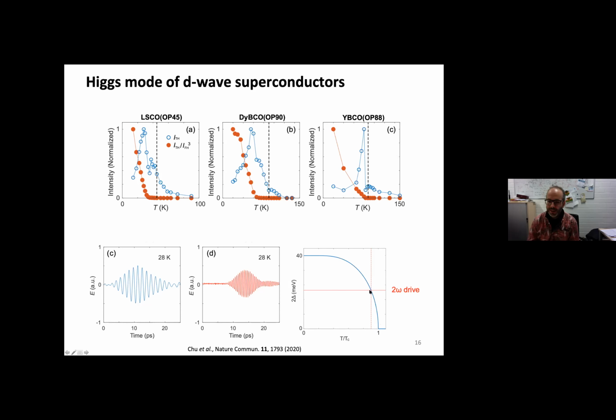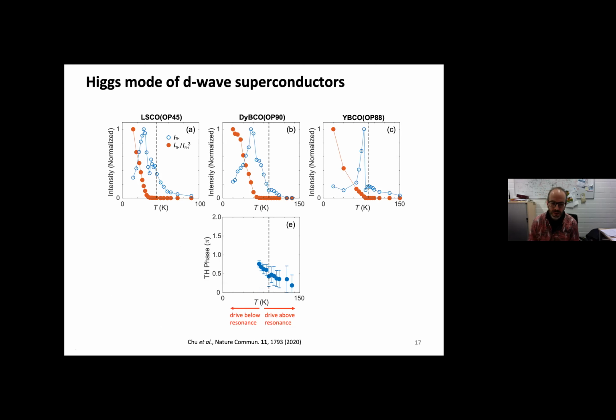So basically we are changing the resonance of our oscillator by tuning the temperature in the superconducting system. And then if we would sit at this point, for example, that would be our 2 omega equals 2 delta resonance condition in the system. And then if we are at temperatures below this, this would really correspond to a drive of our system below the resonance frequency. On this side, this would really be like a drive above the resonance frequency in our system. And if we now do this experiment and we look at this dysprosium, then we see indeed, okay, above TC, there's only a smooth evolution. Maybe there's a very tiny jump of the phase of the system.